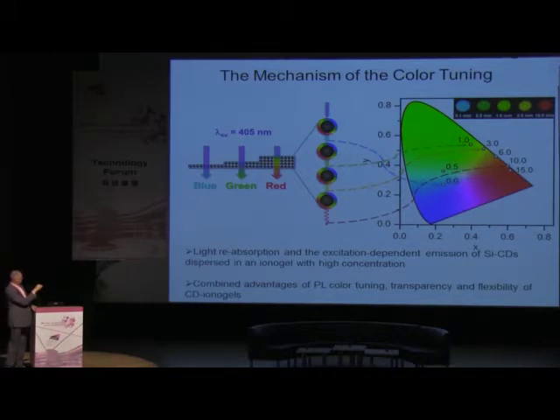So how does it work? If we excite a thin film, then propagating light essentially excites some amount of carbon dots like it would in a diluted solution. So there is very little reabsorption and re-emission for thin films. If you go for thicker films, then at some point along the pathway, carbon dots will be excited. They will re-emit light at wavelengths shifted to longer wavelengths. Then that emission will excite the next portion of carbon dots, and because the emission is excitation dependent, the outcoming light becomes green. And if the pathway becomes longer and longer, there will be a number of these reabsorption and excitation events, and by that we shift the emission to the red. And by that we can achieve full color tuning depending on the thickness of these materials.